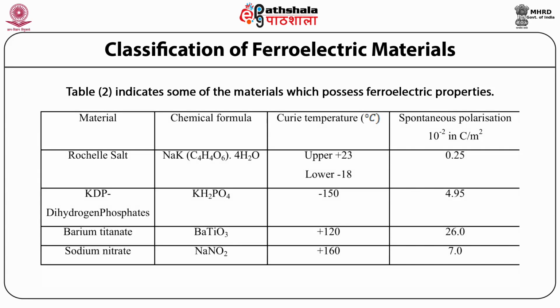For example, Rochelle salt, that is sodium potassium NaK C4H4O6 with 4 water molecules, has a Curie temperature upper of 23 and lower of -18. Spontaneous polarization is 0.25, which is highest for barium titanate. The Curie temperature is 120 degrees centigrade and spontaneous polarization is 26 × 10^-2 coulomb per meter square.